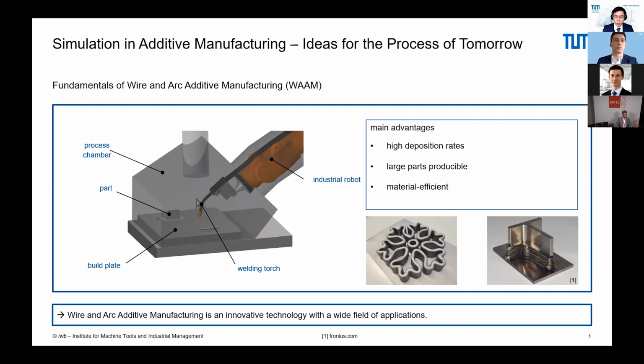We have an arc welding process here, so the thermal energy to melt the wire is generated by an electric arc. We guide the welding torch parallel to the build plate while welding. We receive a weld seam, and if we repeat this process layer by layer in a controlled manner, stacking the weld seams on top of each other, we receive a three-dimensional part. Printable materials are all weldable materials such as steel, aluminum alloys, or also titanium alloys.